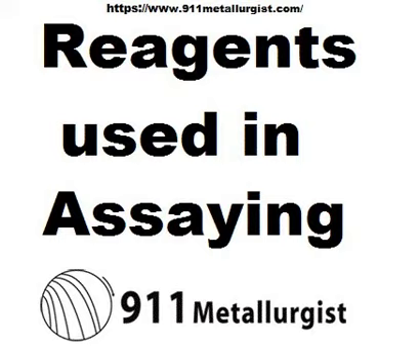During the solution of the metal, red fumes are given off, which mainly consist of nitrogen peroxide. The solution is often coloured brown or green because of dissolved oxides of nitrogen, which must be got rid of by boiling. Generally some ammonium nitrate is formed, especially in the cases of zinc, iron, and tin, when these are acted on by cold dilute acid. Sulfur, phosphorus, and arsenic are converted into sulphuric, phosphoric, and arsenic acids respectively, when boiled with the strong acid. Dilute nitric acid: dilute one volume of the strong acid with two of water.